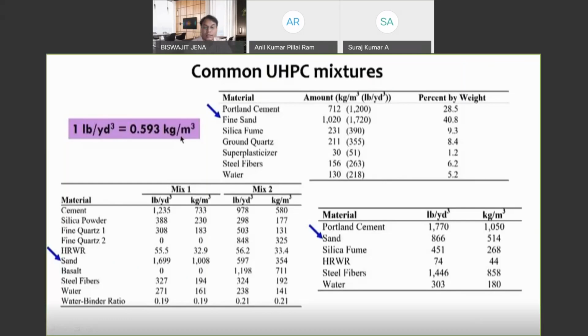Anybody who has worked with concrete and mortar knows that the flowability of a mortar is much more controllable than that of concrete, because in concrete you really have the problems of bleeding and segregation, if your quantities are not proportioned correctly. So one reason why most ultra high performance concrete uses sand is to make sure that the flowability criterion is satisfied. And you will also see in these tables a lot of other fine powders, like silica fume, ground quartz, etc. So a lot of different types of fine powders are generally used to make sure that we have a wider particle size distribution to fit in all the pores.